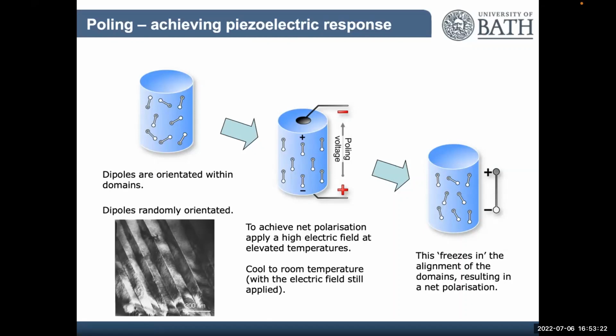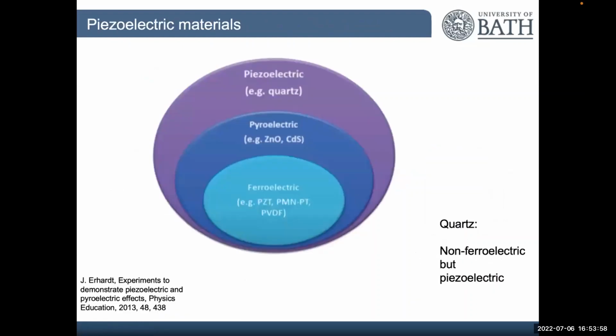To make our ferroelectric active, we have to align those dipoles within the material, and we do that with a poling process where we apply an electric field, a few kilovolts per millimeter, and some heat to allow those dipoles to switch within an electric field, and we align those dipoles. We then cool the material down with the field still applied, and then we take the field off and we have our remnant polarization and a macroscopic polarization across the material. As Haito indicated really nicely, we work on ferroelectric materials because we can switch them exactly as I just showed. We can apply an electric field and switch those dipoles, and all these ferroelectric materials exhibit a pyroelectric response because the polarization changes with temperature. Likewise, all these ferroelectric materials exhibit a piezoelectric response because, again, the polarization changes with stress.